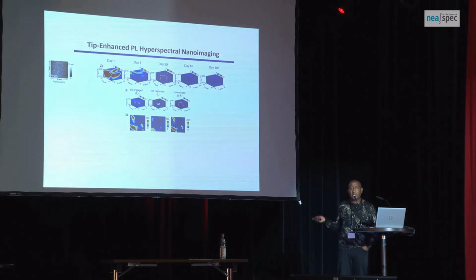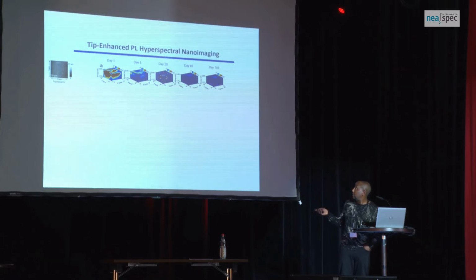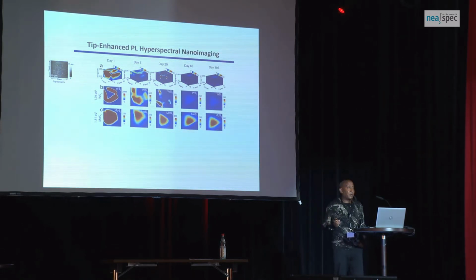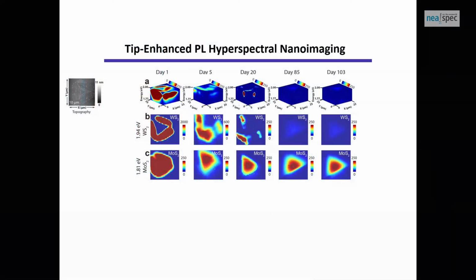Someone asks, we can go talk about this, but this is the data I want to focus on. If you take a section cut of this cube at 1.94 eV and 1.81 eV, which are near the band gap of WS2 and MoS2 respectively, these are the neutral exciton emission. You notice something like this. This is just a section cut of the top panel at these two energies, over time.